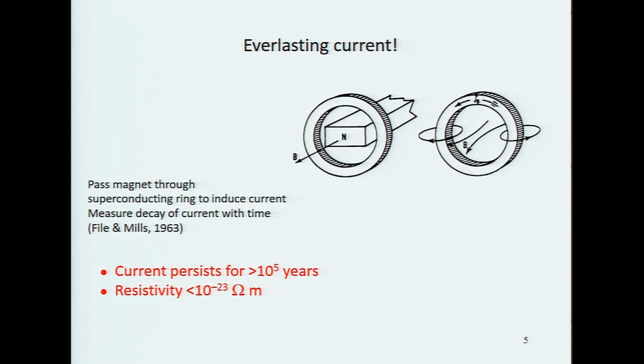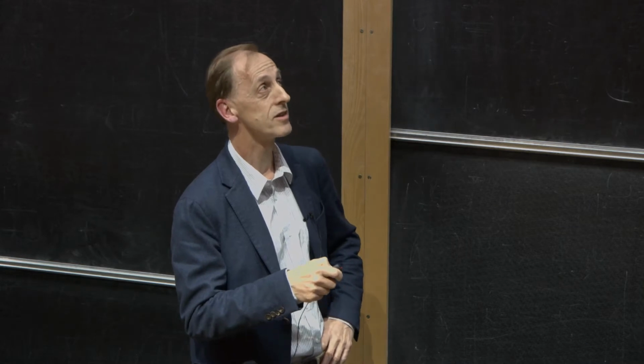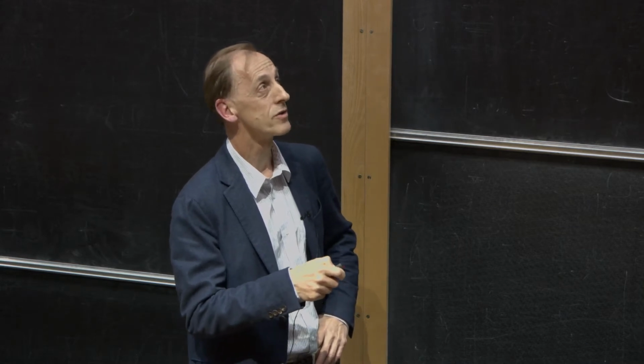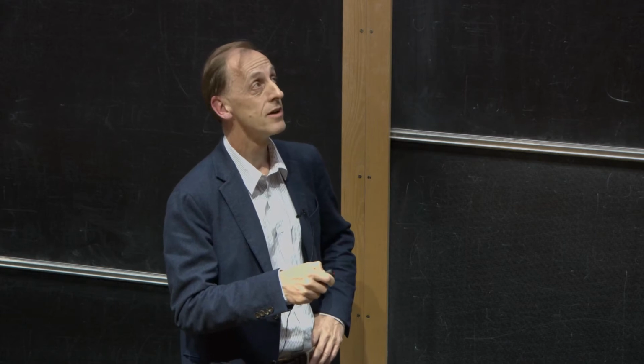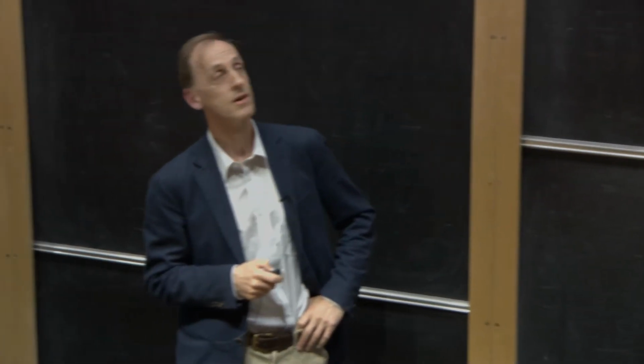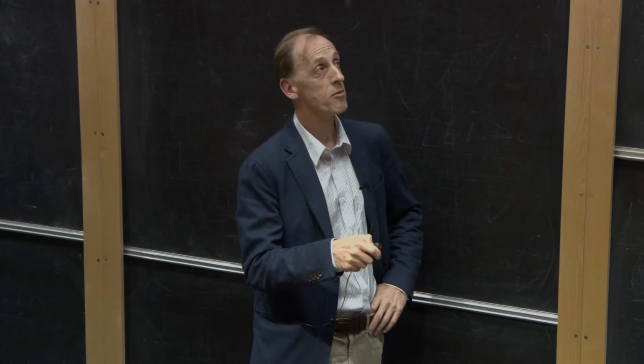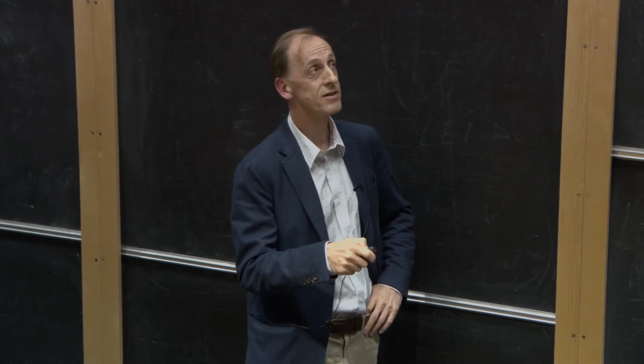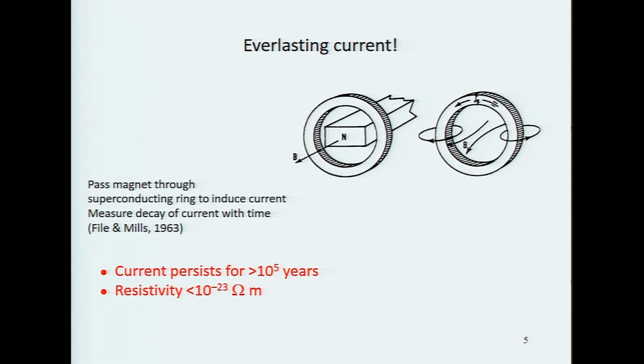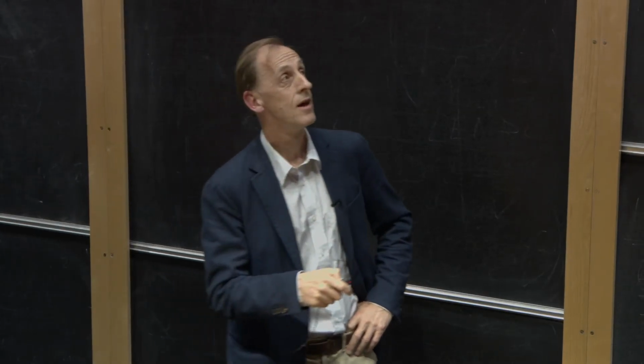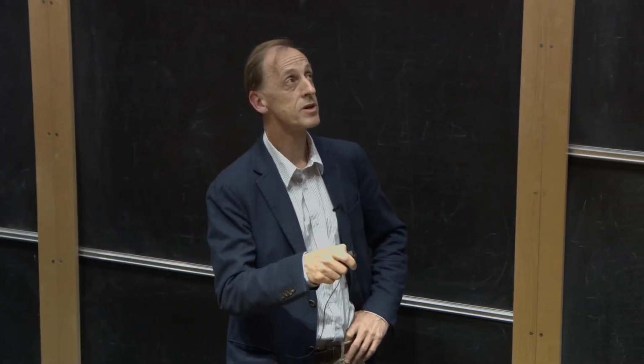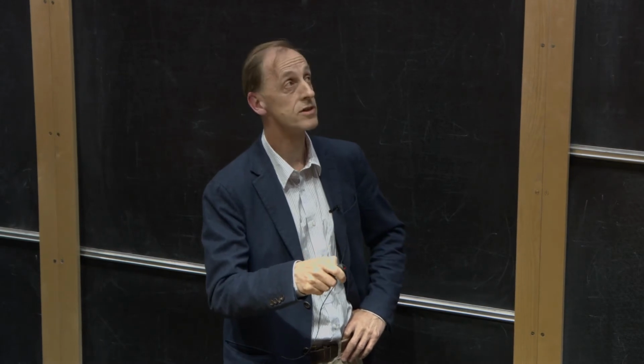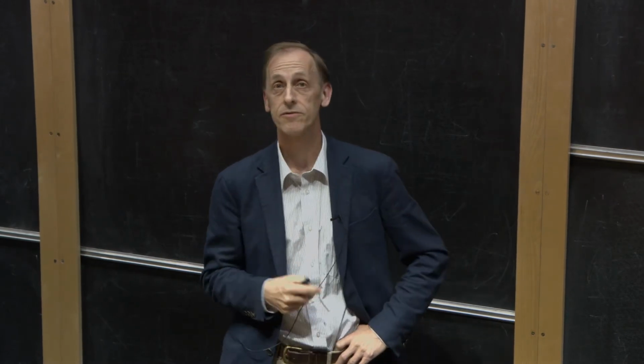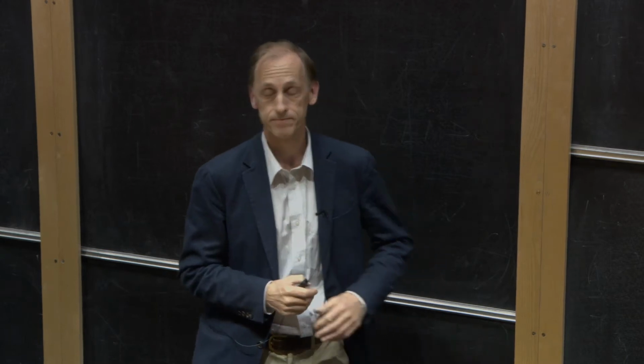So from that value, in fact, they could calculate that the resistivity of their loop was not greater than 10 to the minus 23 ohm meters. Remember I said before that the resistivity of copper is 10 to the minus 9 ohm meters around room temperature. So this is 14 orders of magnitude lower resistance than the resistance of copper. And we now believe, in fact, that in the superconducting state, there really is zero resistance, so that this current here is the nearest thing we have on Earth to perpetual motion.